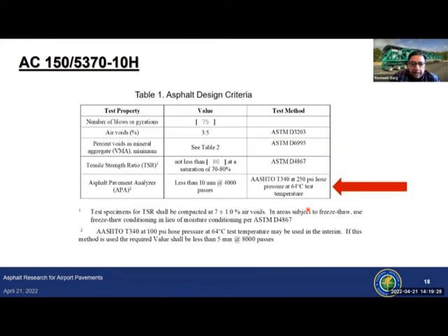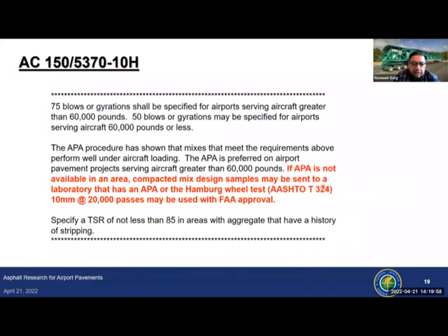And then it added the APA test as the performance test to limit rutting. And we worked with the APA manufacturer to develop an APA that could apply 250 PSI hose pressure. The standard APA applies 100 PSI hose pressure. So we did some research to provide guidance for the 100 PSI APA also, in case the project did not have access to 250 PSI hose pressure. And some states west of the Mississippi heavily use the Hamburg wheel test, so guidance was added for the Hamburg wheel test.